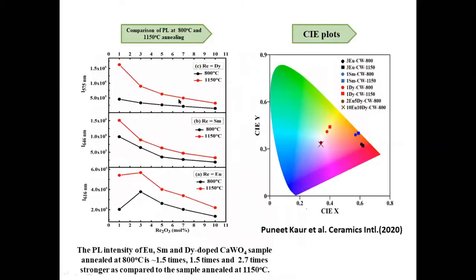And there are also the effects of annealing temperature on the polycrystalline samples. If you increase the annealing temperature to 1150 degrees Celsius from 800 degrees Celsius, your photoluminescence intensity increases significantly. And this work is also published.